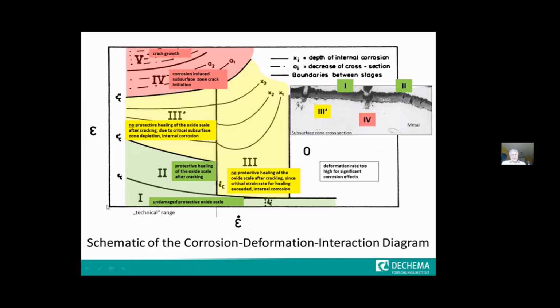Now, after a while, by continuing cracking and healing, the protective subsurface metal like chromium or aluminum is consumed, and the depletion can go so far that no more protective oxide can be formed and no healing can take place anymore. Then we end up in a situation as given here in 3', so that no more protective healing can take place.